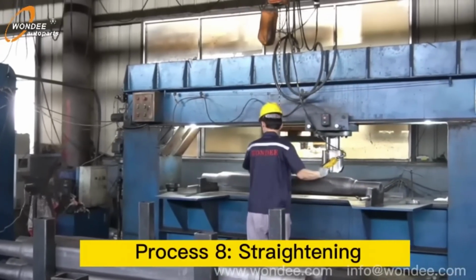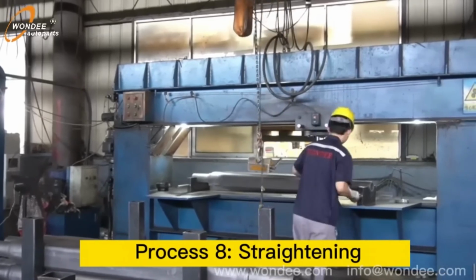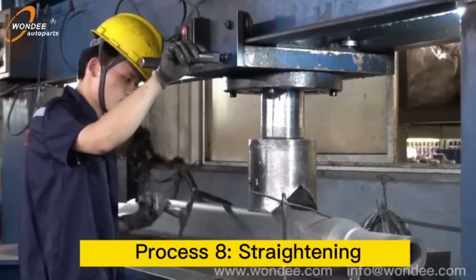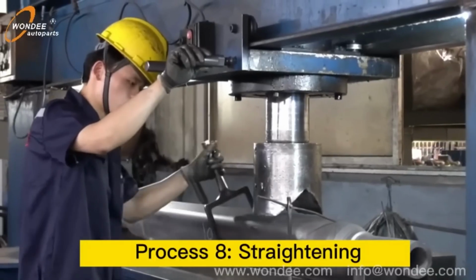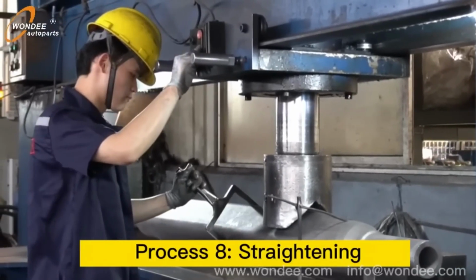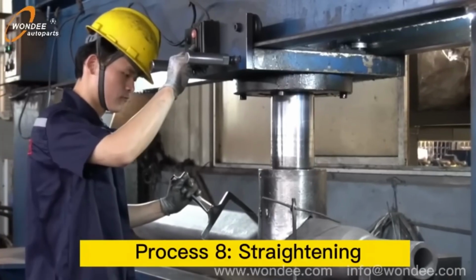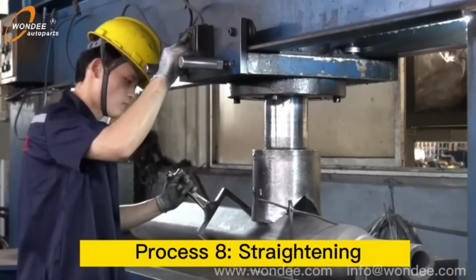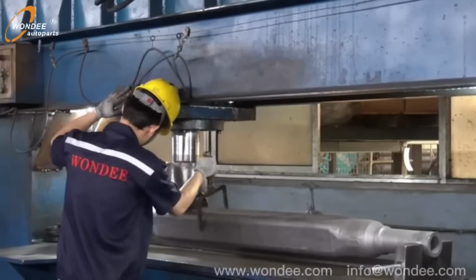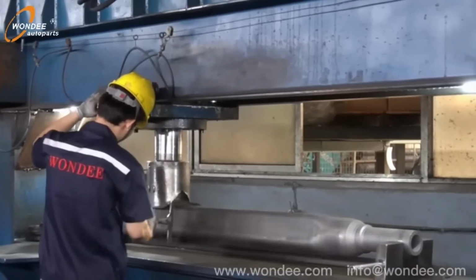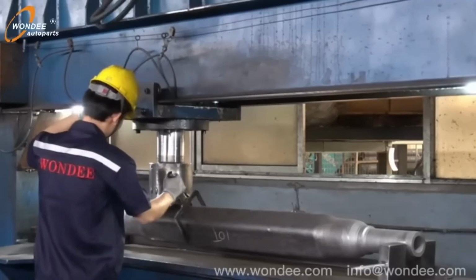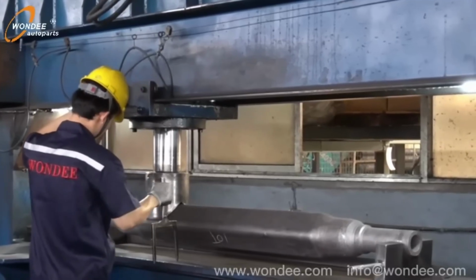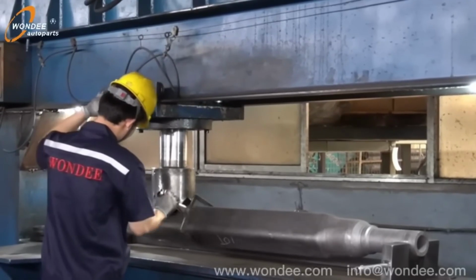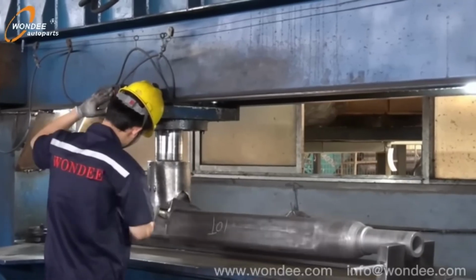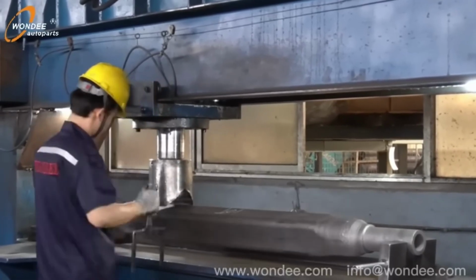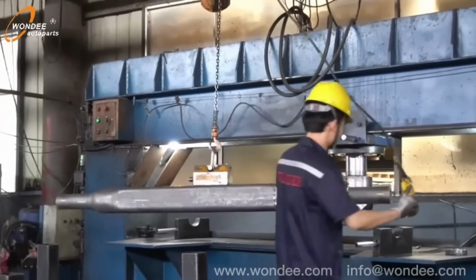Straightening corrects any bending or deformation that occurs during earlier processes like rolling, heat treatment, or cooling. The axle is placed into a hydraulic or mechanical straightening machine, where precise pressure is applied at calculated points along its length. Skilled operators or automated systems measure runout and adjust the force to ensure perfect alignment. Accurate straightening is essential for axle performance, as even slight bends can cause vibrations, uneven tire wear, and premature bearing or suspension failures in service.